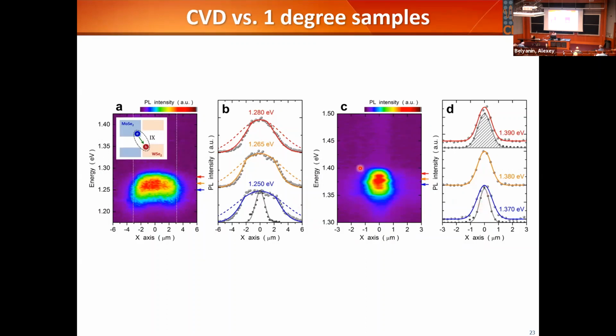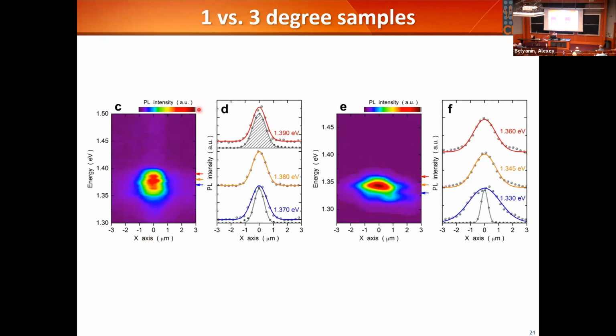So we cannot tell if the exciton is moving. We have not proved they're perfectly localized in the individual cell because we don't have that spatial resolution. But we can say they do not move beyond the micron size we can see. And then we can also compare two samples, 1 degree versus 3 degree.